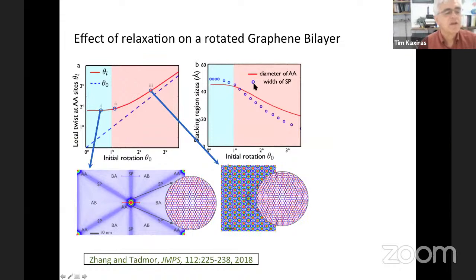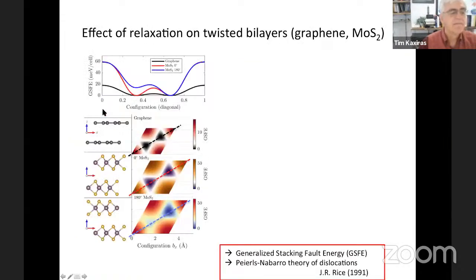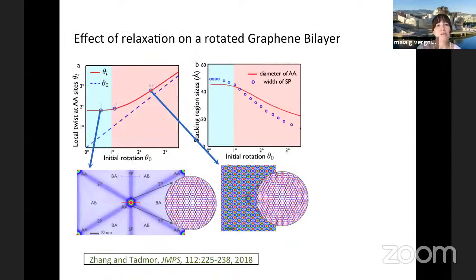And this is the width of these, which are called saddle point configurations or domain walls. So these domain walls become smaller and smaller in width as the angle increases, and they acquire a roughly constant size at small angles. And the behavior changes at around 1 degree, near the critical or so-called magic angle. So below the magic angle, you have constant diameter of these AA regions and constant twist angle.